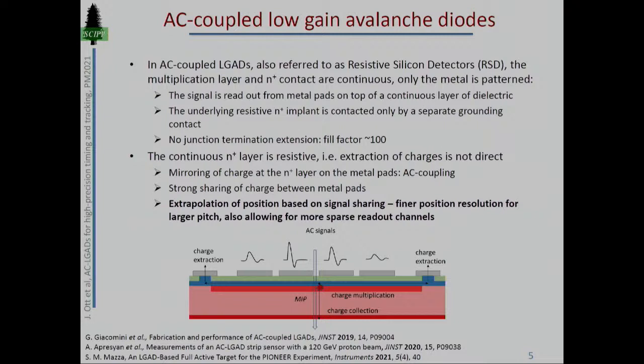The signal, or the charges, are collected at a resistive N layer, so they're not collected immediately, and the signal is then capacitively coupled over the dielectric as an image charge on the metal pads. Finally, what this results in is quite significant sharing of signal charge over the metal pads, and we can use that to extrapolate for position resolution.